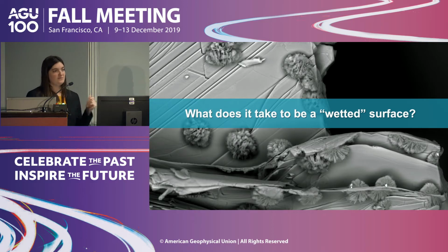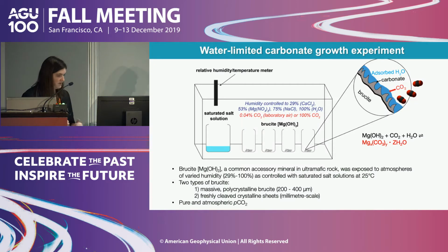All right, so these columns suggested that we didn't need too much water to have a wetted surface area available for reaction, but we wanted to delve into this a little bit further and better define, well, what is a wetted surface area? How much water do you really need for these reactions to occur? And so to do that, we conducted a series of experiments where we grew magnesium carbonate minerals under extremely dry conditions. And so by extremely dry, I mean we had no visible liquid water available. The only water available for reaction is humidity in the atmosphere.